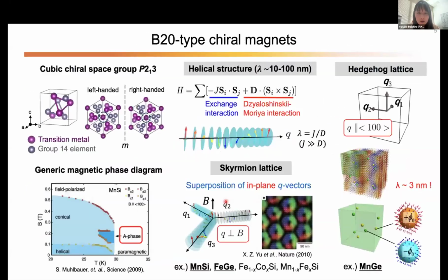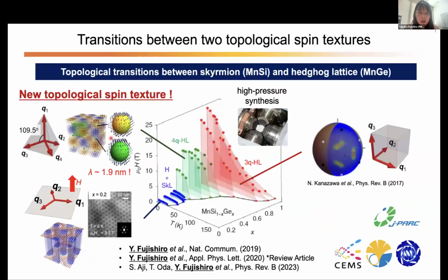So let me introduce my first work. In this work, we explored a transition between two different topological spin textures, which is the conventional skyrmion lattice in manganese silicide and the hedgehog lattice in manganese germanide, by making a new solid solution, manganese silicon germanium, which was synthesized for the first time using high pressure synthesis.